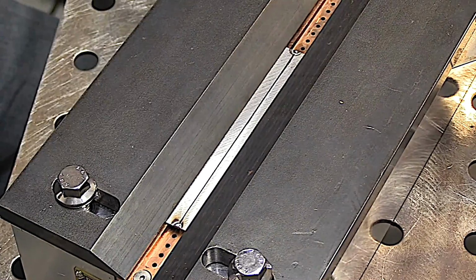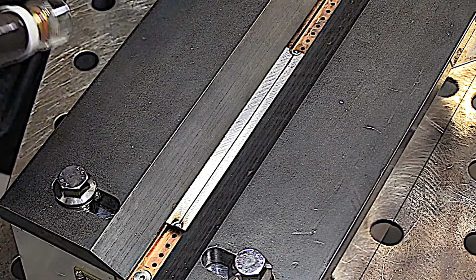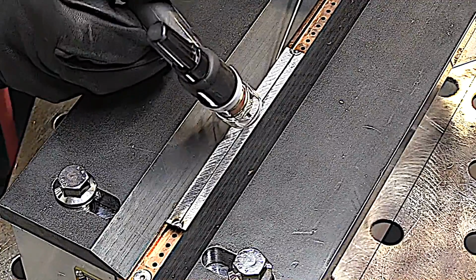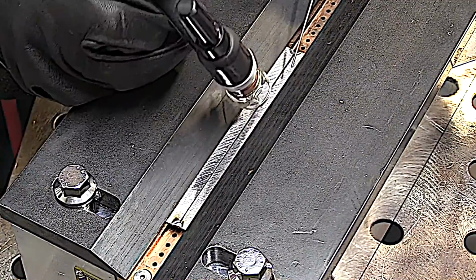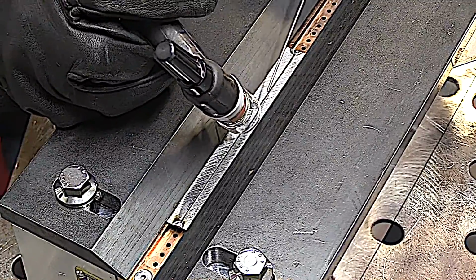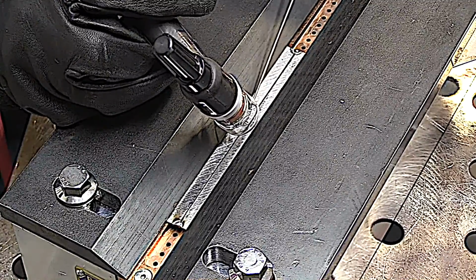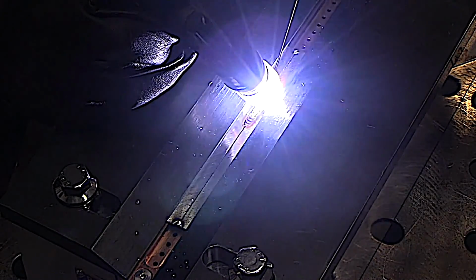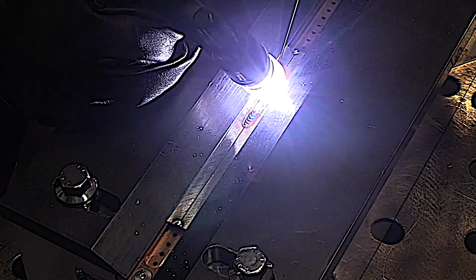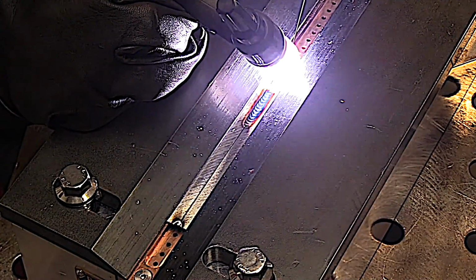The aerospace welding specification allows for some melting ends away, but when I used to administer this test, I didn't allow that because all of our parts had ends that we didn't want to melt away. I was probably lenient in other areas that I didn't feel were as important, but melting ends away is something I felt like was super important. So the way we administered this test was to start in the middle and weld to one end. That way we could require a stop and a taper off and a crater out taper off in the middle to demonstrate the ability to not leave a crater crack, which is another thing I felt was super important on aircraft parts.